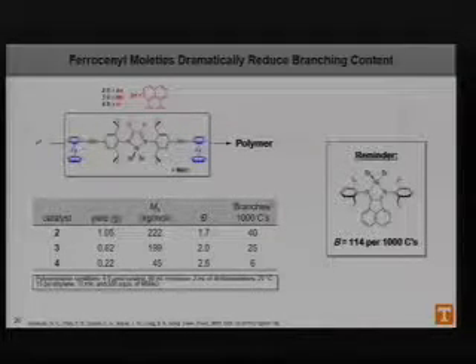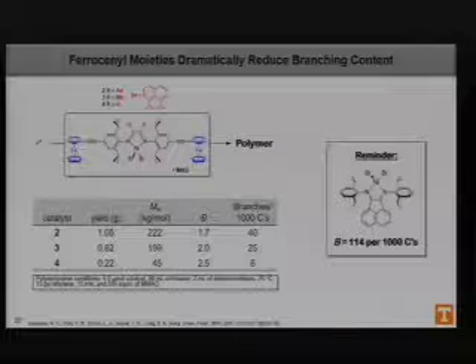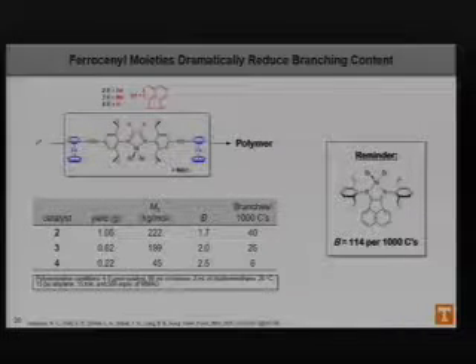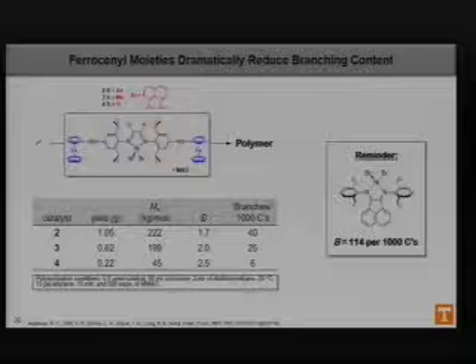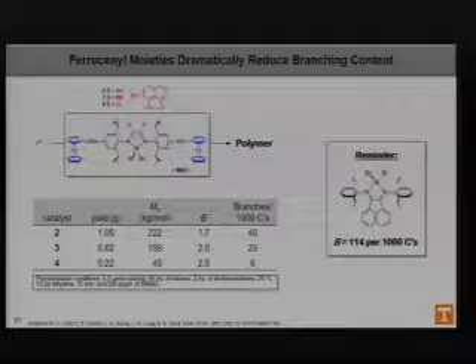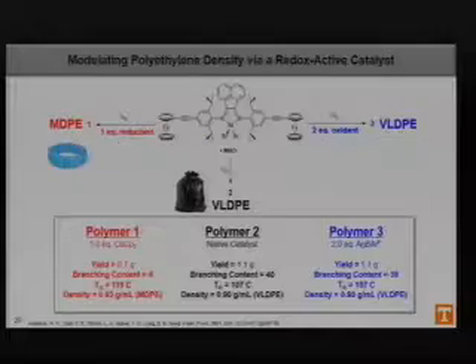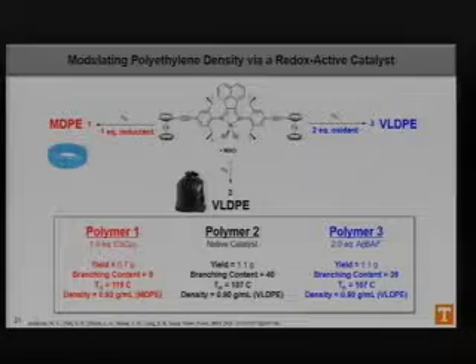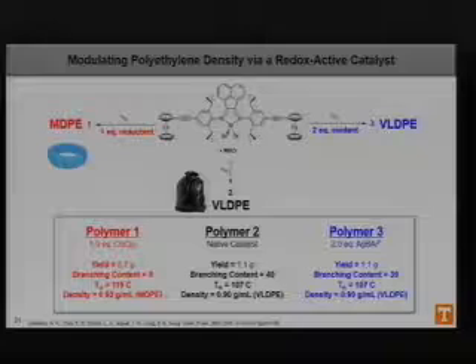So then, because of the very high yield and the moderate branching content that we achieved with the acenaphthene catalyst, we focused on it for the rest of our polymerization results. And we found that if we were to take our catalyst in its native state, we would produce very low density polyethylene. This was the 40 branches per 1,000 carbons that I showed before, and that has a density of about 0.9. And this is similar to a trash bag type material.